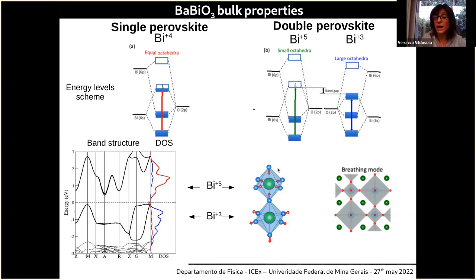So the oxygen octahedra around 5+ is shrunk with respect to the one at the bismuth 3+. And here is a projection of this breathing mode in this material, right? So here you can see that this is perhaps the main physical mechanism that will determine the properties of this material. This is the close relation between the structural distortions and the collective modes of the structural dynamics with the electronic degrees of freedom. When they are all equal, they are metallic, and when you have this charge order phase, you have a semiconductor. And it is with the charge disproportionation. I should say that in the charge disproportionation, there are not exactly two electrons of difference. It is much less. This is just a formal balance because these are hybrid orbitals, right?